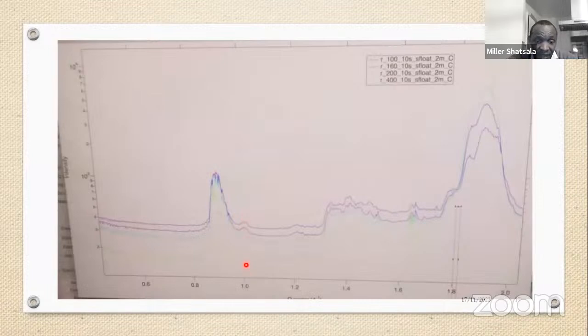So at this phase, we expected to get a peak at 1 and at 1.4, so that it can tell us that a perovskite film formed. Unfortunately, this perovskite peak, as you can see, has gone down. But the one which has come up is the one at 0.9. It shows that our perovskite film has degraded back into lead iodide. So it shows that temperature affects the perovskite film. Why we are interested in this is because we want to optimize the film formation temperature and humidity, so that we can produce films that are stable for some time, and we can use them for commercialization of perovskite, which is almost phasing out silicon technology.